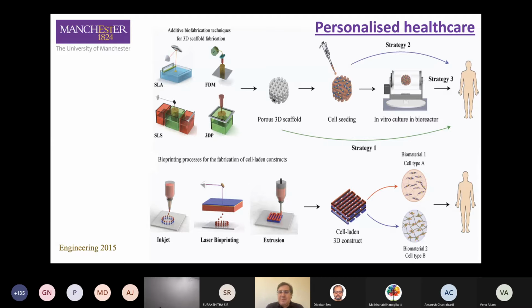This is the same. So we use additive manufacturing to create these porous molds, these scaffolds, and then these scaffolds are seeded with cells, and the molds will give shape to the cells. The cells will grow, and during this growing mechanism of the cells, the initial mold will disappear. So by the end, we have a new tissue. So we can pre-culture the structure in a bioreactor before implanting the structure into the body, or we can print, seed it with cells, and implant directly into the body. So this is one strategy that we are focusing.